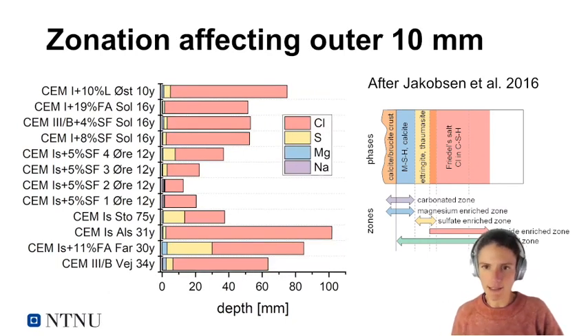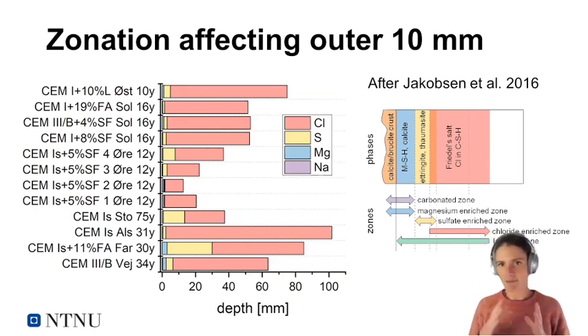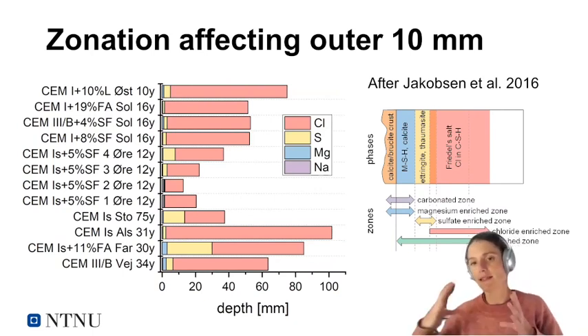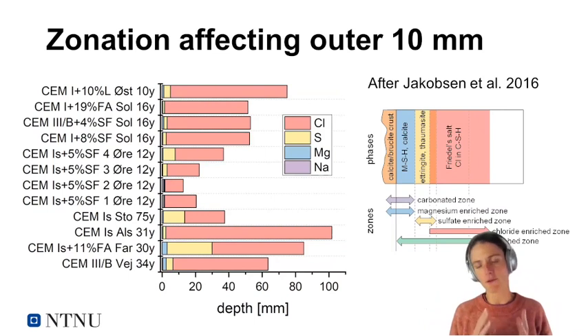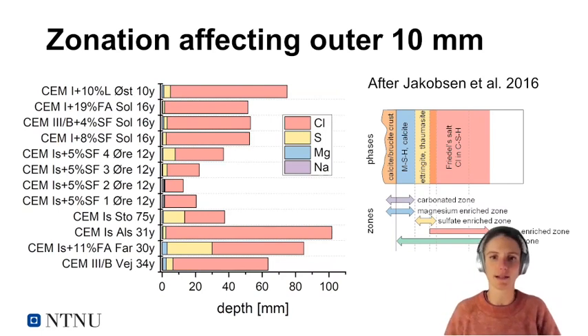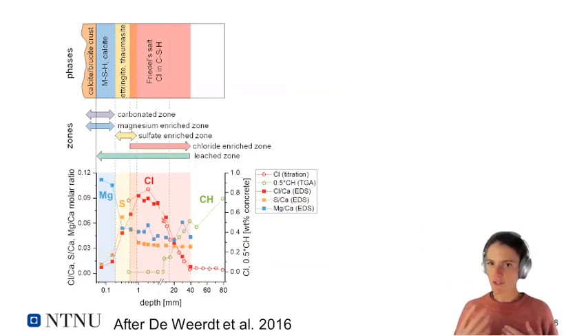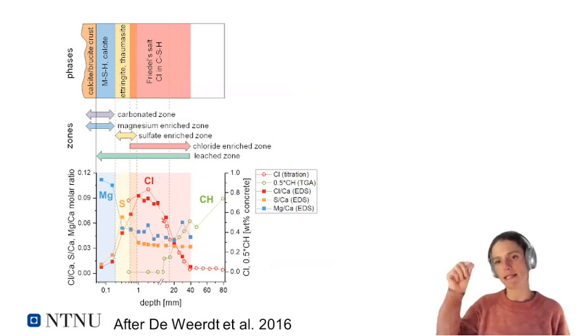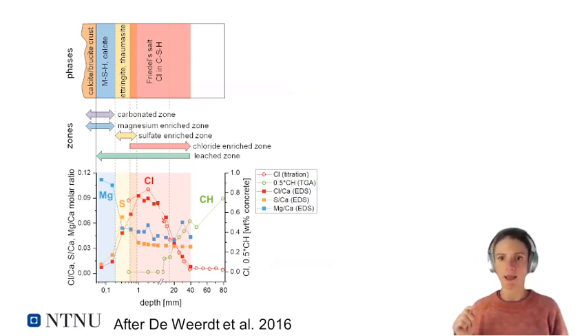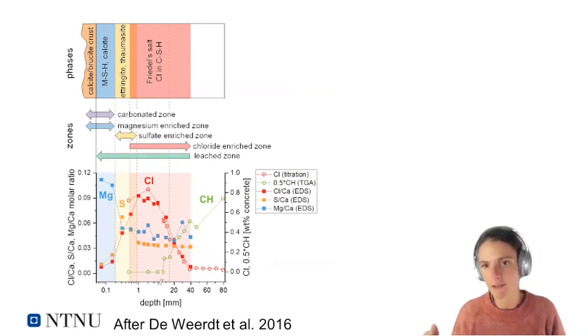If we change this into a linear scale, you can see that this magnesium and sulfur-enriched zone is relatively narrow. So the chloride-enriched zone is the one reaching the deepest. But at the surface, we systematically have the magnesium-enriched zone, the sulfur-enriched zone, and then the chlorides. So just to illustrate how we detect these zones, I have one example here. It's from the field exposure site where we had these beams hanging from the ferry dock. And these are elemental profiles, which I determined with the scanning electron microscope and EDS.